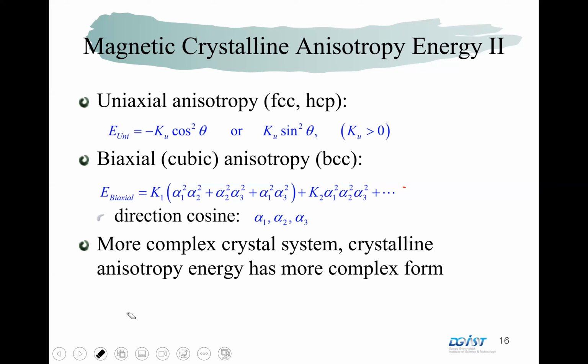Okay. Her question is about the relation with the uniaxial anisotropy and the PMA, some specific crystalline directions. Okay, so PMA has many kinds of sources, and now we are talking about only the crystalline energy. But many kinds of PMA came from the surface energy. So surface energy is a little bit different from this crystalline one. But some crystalline energy, for example, the most famous example is the cobalt platinum or iron platinum L10 ordering.